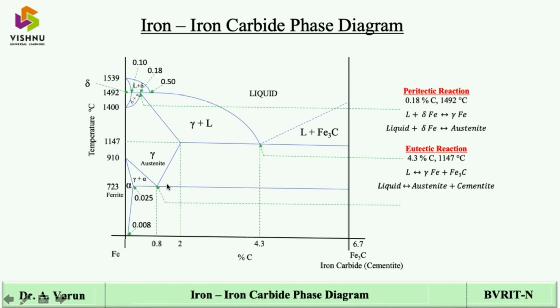The third invariant reaction occurs here at this point, at 0.8 percentage of carbon and 723 degrees centigrade, which we call a eutectoid reaction. So at 0.8 percentage of carbon and 723 degrees centigrade, we have the eutectoid reaction, which is again gamma transforming into the ends of the line. This end it is alpha and this end it is Fe3C. So the austenite will transform into ferrite plus cementite, and this mixture, ferrite plus cementite, is called pearlite.